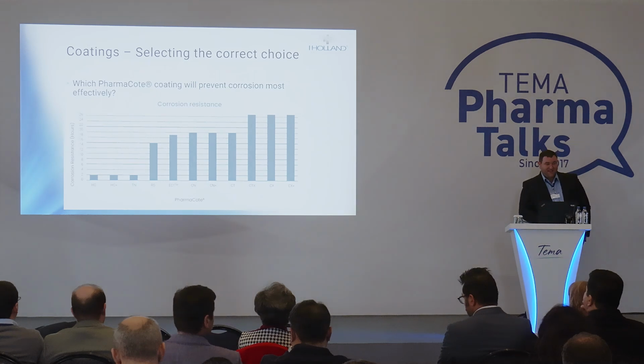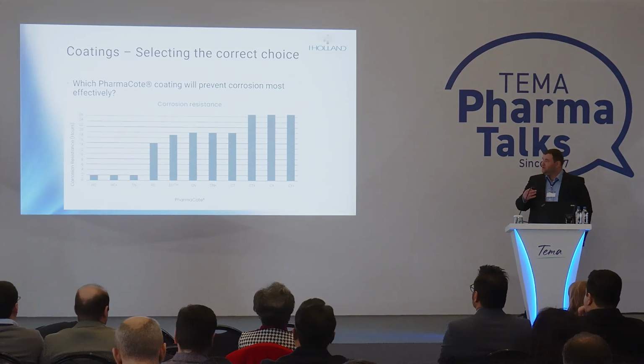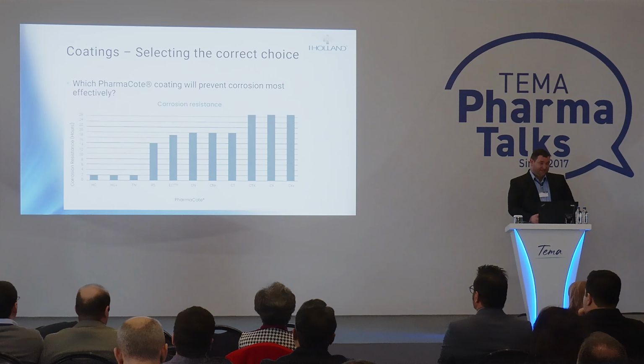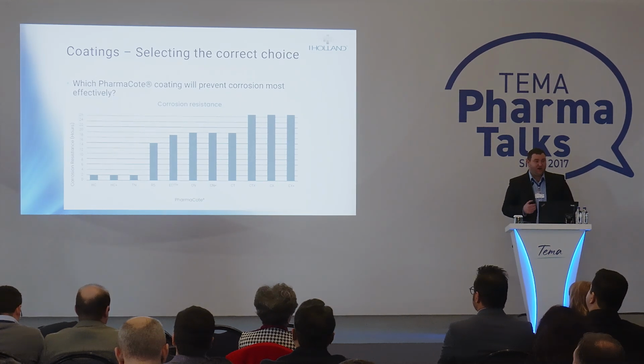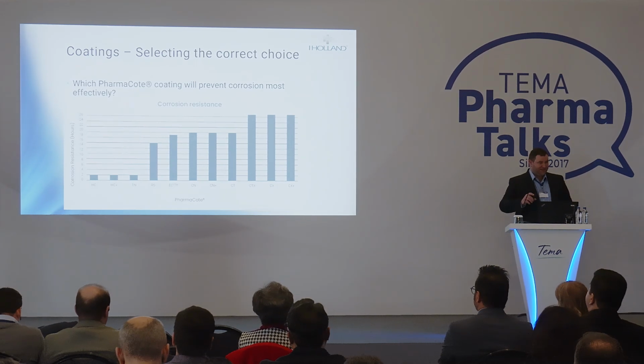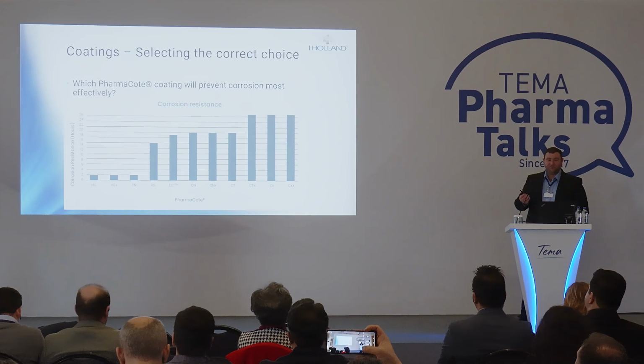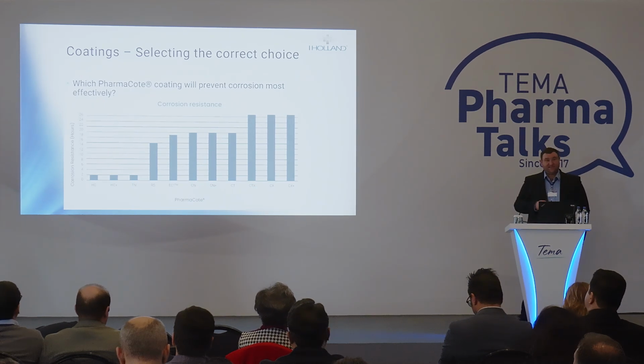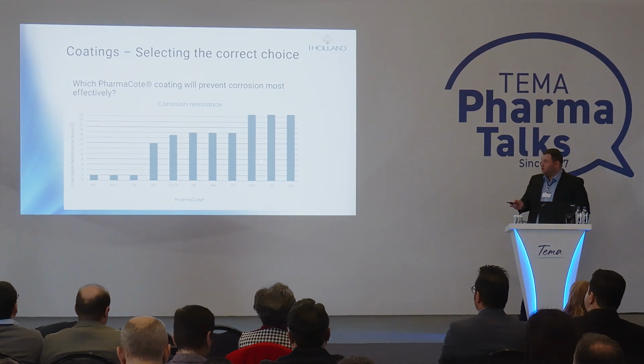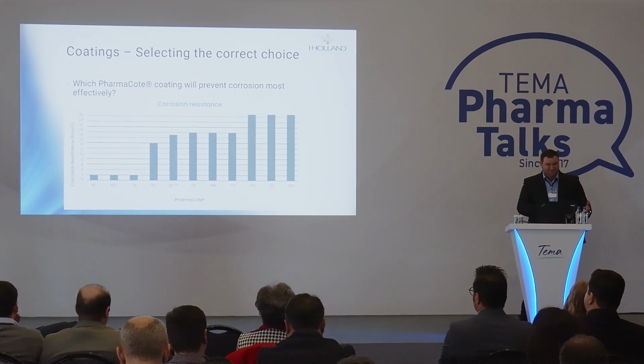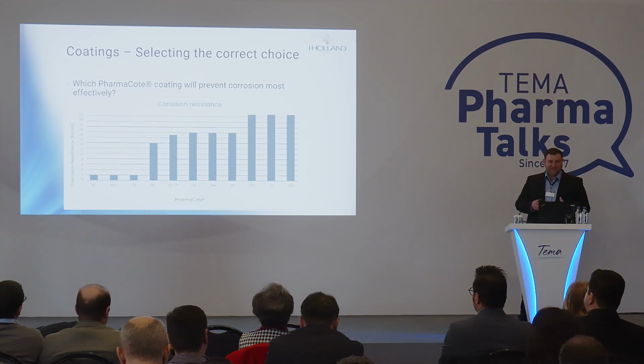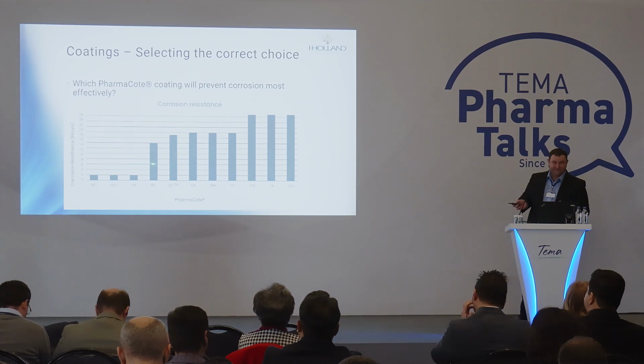Corrosion resistance, again, is quite easy to select. The coatings are all tested, and in fact our steels are also tested under extreme environments. We salt spray test our steel. It's put in a chamber and salt water is sprayed at it, and we go back and check it every 2 hours. All of our steels, including stainless steel, show corrosion after 2 hours. Now this is very aggressive testing, so it's not going to impact what you see in reality, but it gives you an idea of just the difference coatings can make.